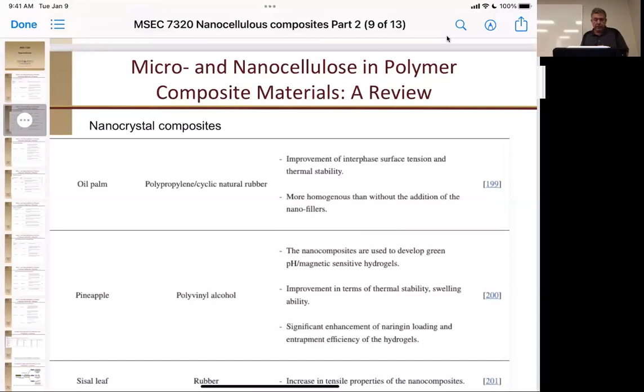Okay, so I don't know how they extracted it out of pineapple. I assume it might be just the tops, but not necessarily the fruit. I didn't figure that part out. And with polyvinyl alcohol, it's a great substrate for the system here, used to develop green hydrogels, pH sensitive and magnetic sensitive hydrogels. So they're swelling them and looking for the properties, improved thermal stability and swelling ability. Okay, because it's acting as those crosslinks, it gives you a more stable swollen material, significant enhancement of loading and entrapment efficiency. That's, I believe, a dye that they're using for water